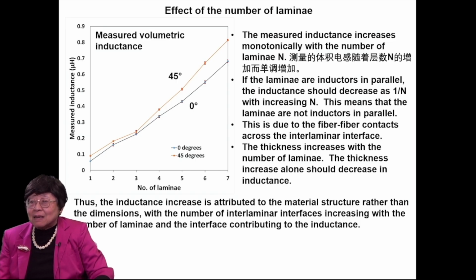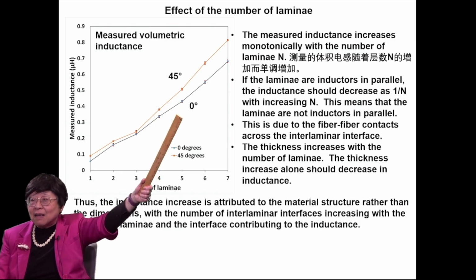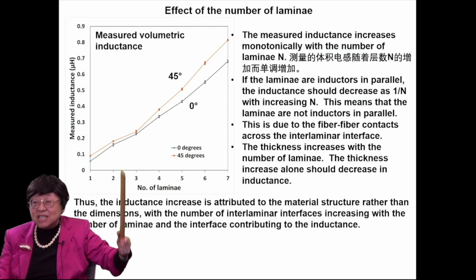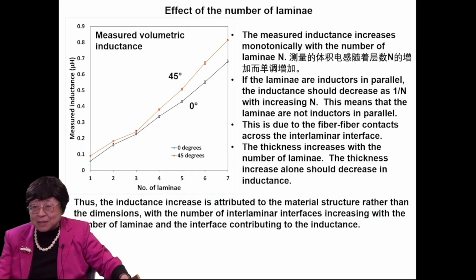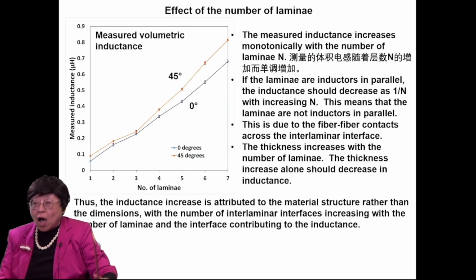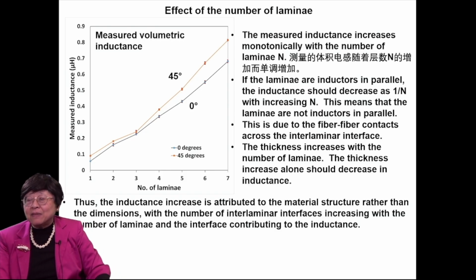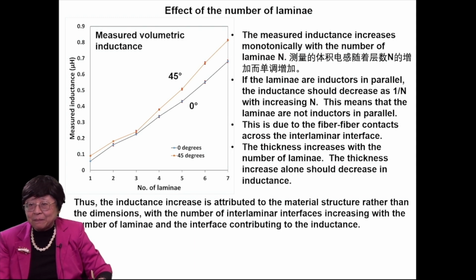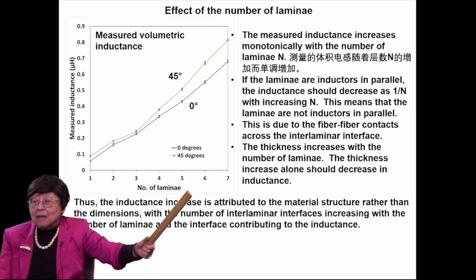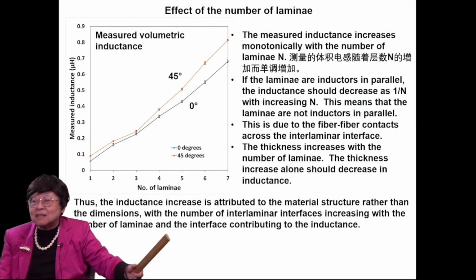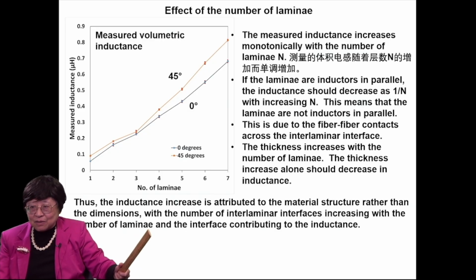This means that the laminae are not inductors in parallel. We have the inductance increasing with n, but if it were inductors in parallel, it should decrease with increasing n. It's the opposite. And so this means that the laminae are not inductors in parallel at all. And this is due to the fiber-fiber contacts across the interlaminar interface, so that the interlaminar interface contributes to causing the inductance increase. So the more the number of interlaminar interfaces, the higher is the inductance.